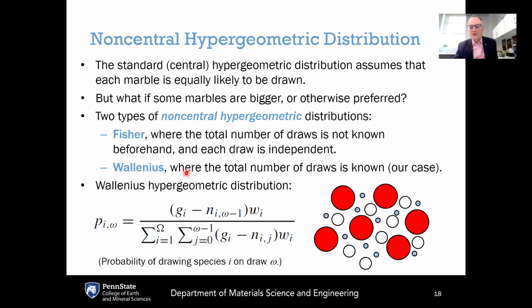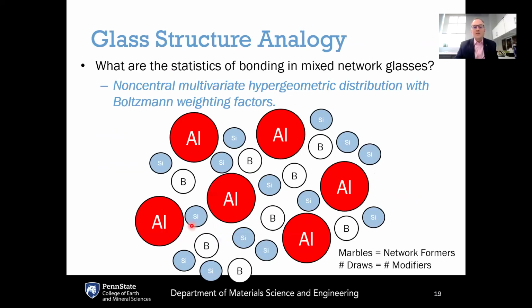Our case for glass structure follows the Wallenius distribution, and that's shown here. This is the probability of drawing a different species i on the omega-th draw, where you've got different weighting probabilities that are given by the W sub i's, the different number of species here, and the different number of draws. And so, for example, with this glass structure analogy, suppose that you've got a boroaluminosilicate glass, and you've got a certain number of aluminum atoms, certain number of boron atoms, and a certain number of silicon atoms. The number of atoms is governed by the composition of the glass, so the chemistry of the glass. And the number of each atom dictates the relative entropy.